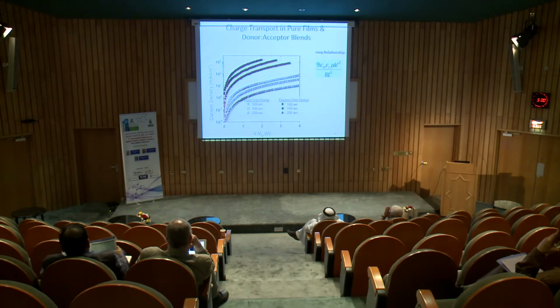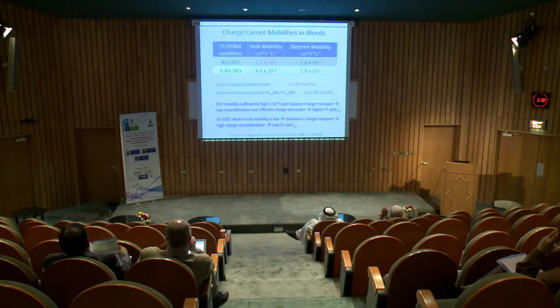This is the type of data that you measure using these single-carrier diodes. We measure the current density as a function of voltage, and then we use the Mott-Gurney relationship to extract the charge carrier mobility, and this is the device result for that. First, we also measure the transport in our pristine donor material. We have a hole mobility of about 5 × 10⁻⁴ cm² per volt per second, and the electron transport in the pristine PCBM is around 1 to 2 × 10⁻³ cm² per volt per second.